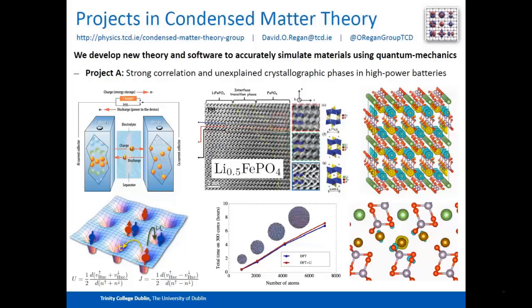So normally when you do a DFT calculation, you look at the fully charged state and the fully discharged state. When all the layers are full of lithium, or when they're all empty, and you take the total energy of the two states, you take a difference, you can at least calculate the voltage of the battery. Now I don't know about your phone or your car, but mine spends all its time somewhere in between, fully charged and fully empty.